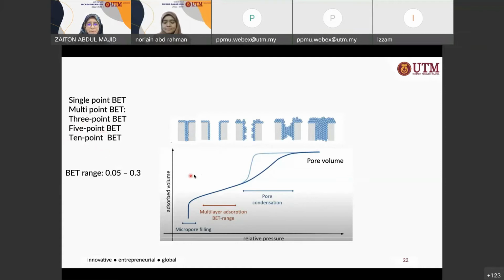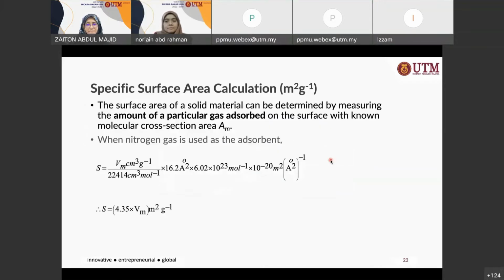Okay. So if you have a look at the pore filling here, just to show you, this is the micropore filling. You notice that the micropores are very small, less than 2 nanometers, so they automatically fill up. And then you start the multi-layer filling and so on. And this is your saturation. This is your pore condensation, whereby the hysteresis loop. And this indicates the saturation pressure. And this is actually where you can determine your pore volume. This is another view of the explanation.